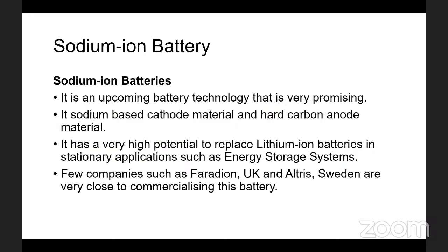Let's talk about sodium battery. Sodium-ion battery, a lot of people, in fact, one of the earlier speakers, was also talking about that it's being developed. In fact, I'm testing some of these cells also. Like Mr. M.K. Srivastav said, 3 voltage, yes, 3.05. Good cell. But to be honest, nothing can be spoken about the cycle life. Even if someone wants to put it in PLI or take it to a very high cycle life, I would have my own suspicions because it's a very new material. Nobody has real data of even 3,000 cycles. So looking at very high cycle life for this would be a little bit difficult.